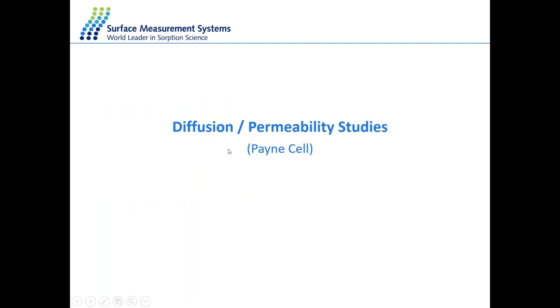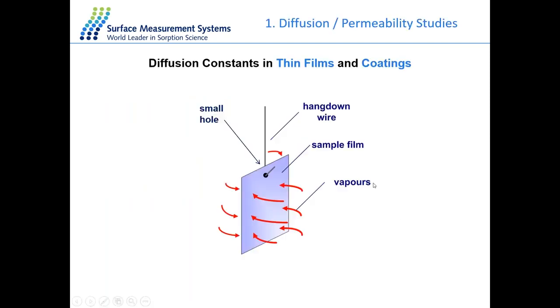So the first one is the diffusion and the permeability studies. To measure the diffusion constant of some thin film samples, we basically have 2 different ways of performing the experiment. We can either put the whole piece of the film just in the sample pan, and then put the sample pan in the chamber and measure the uptake of that whole piece of film in the pan.